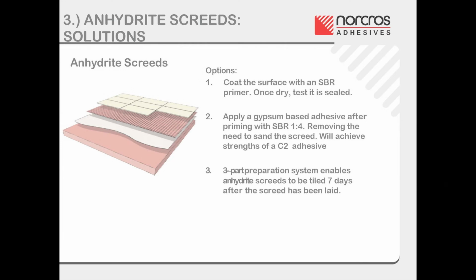BS 5385 states that, if using a gypsum adhesive, only remove loose debris from the surface. There is no need to sand the screed, therefore saving time during installation. In order to ensure the surface is dustproof, prime with a 1 to 4 parts SBR to water mix to suppress any dust that may be on the surface.